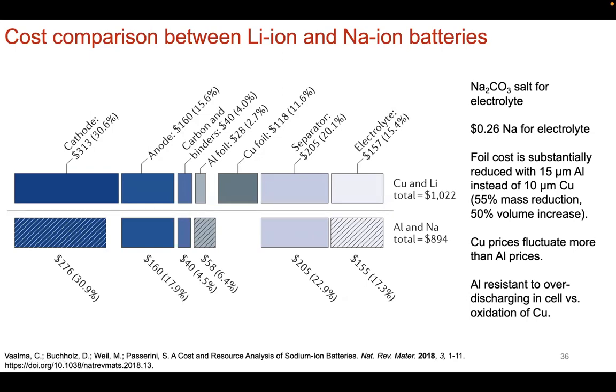And we highlighted the advantage of going from lithium-ion using copper and aluminum anodes to sodium-ion batteries, and the advantage of just using aluminum foil for the anode, because now there's no alloying reactions that you have to think about. So that's why the copper foil is voided out here. So that is an advantage, but the thickness of the current collector increases. Oh, sorry, I said anode, I meant current collector, aluminum current collector, not aluminum anode. Aluminum current collector is a little bit thicker in the use of sodium-ion batteries versus lithium-ion batteries. So it's a little bit thicker, but the offset is that the price is cheaper. There's less of a price fluctuation. So a number of advantages there.